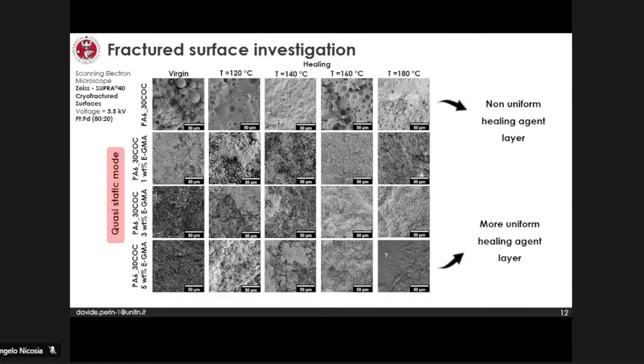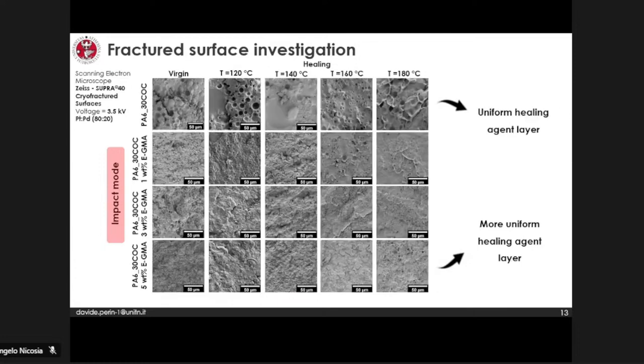Therefore, upon healing, the COC was actually able to flow inside the crack, but was not able to completely fill the crack because the specific surface area developed during the fracture process was too high, and therefore the healing process was not as effective as in impact mode. In fact, in impact mode, the surface was brittle, more, let's say, planar, and in this way the COC was actually capable of flowing in a better way and therefore filling in a better way the whole crack.